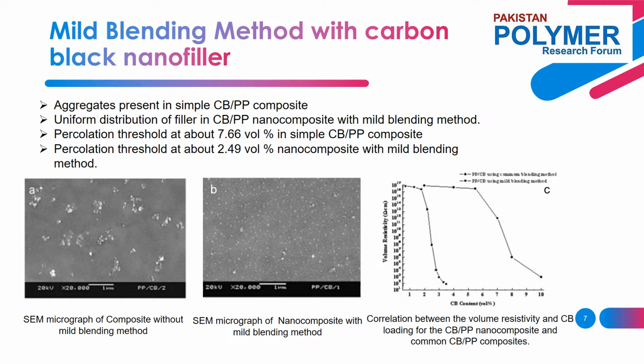The morphological feature of the carbon black and PP nanocomposite prepared using the mild blending method, as shown in figure B, displayed a different structure from the conventional carbon black and PP composite. It was observed that carbon black particles were detached from each other at the nanometer level with a homogeneous distribution in the polymer matrix.